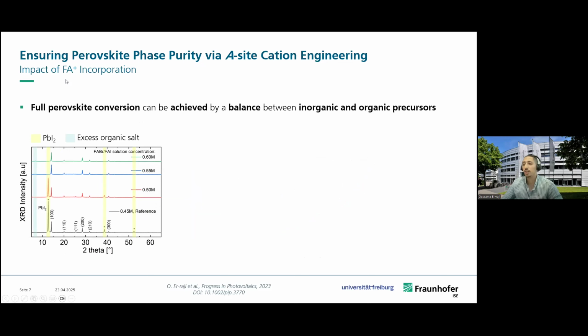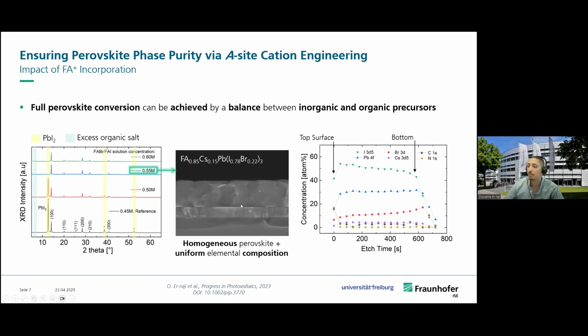And the formamidinium can be increased by just raising the amount of organohalides in the second step, so by increasing the concentration of the solution in the second step. And so here you can see that by going from the reference 0.45 molar gradually up, we can really eliminate this lead iodide peak and have a fully converted perovskite. So you can see this better in the SEM, where now we do not see this lead iodide anymore at the interface. And when looking at the elemental composition of the different elements composing the perovskite, we can see that throughout the depth we have a, let's say, homogeneous elemental composition.